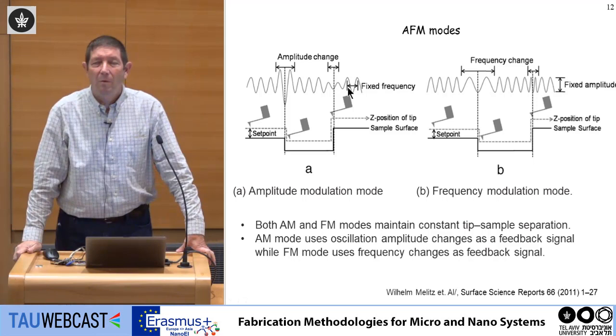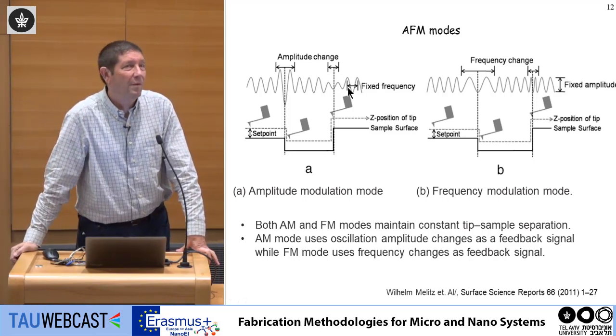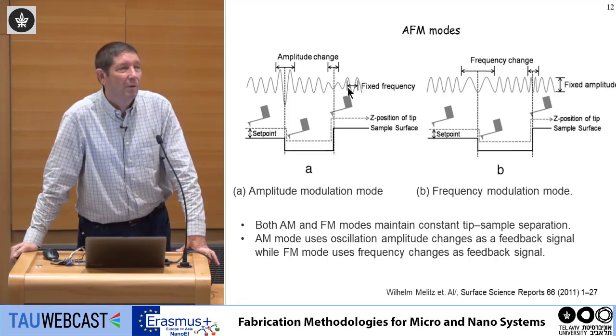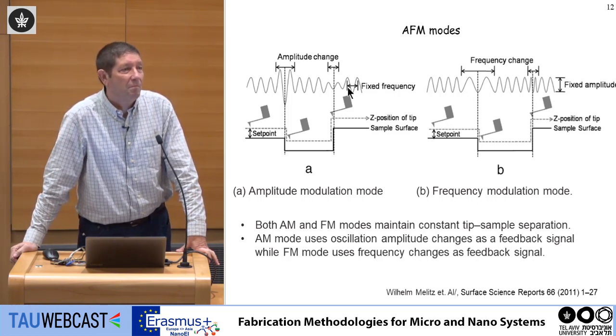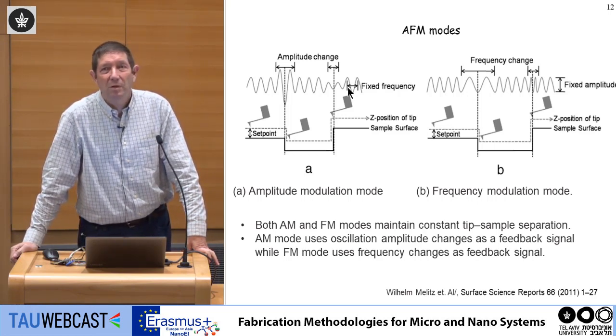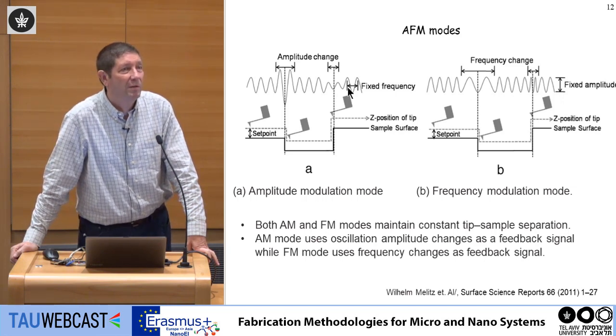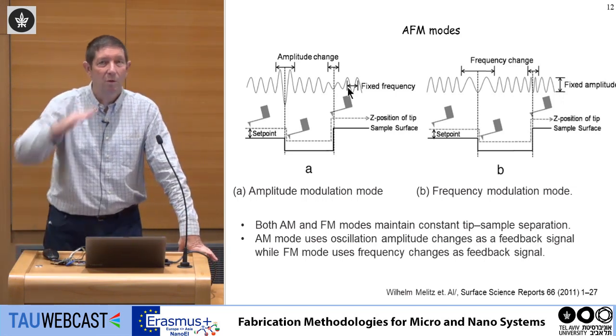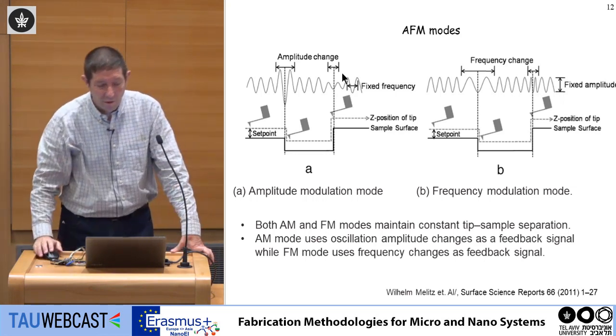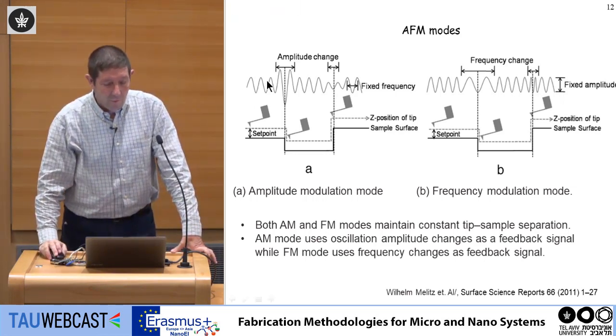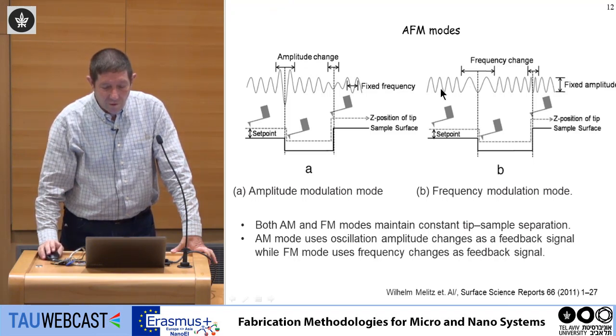Now, why are we doing it? Because you can actually work without modulation. But when you do modulation, it's easier to follow the signal using AC lock-in amplifiers and the AC lock-in mechanism. And you're actually looking for the average. You can identify the average motion, and you can identify the amplitude of the motion. You can also do frequency modulation.